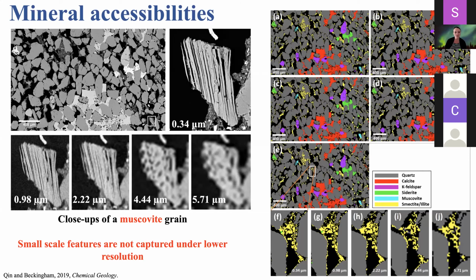So on the left, you can see a muscovite grain, whereas you can see in the highest resolution image, you can really understand the pore structure within the layers, but you cannot see that all in the lowest resolution image. And then on the right, down here on the bottom, is a close-up looking at some of this smectite illite, where you can see the pore structure here really starts to distort as the image resolution decreases.